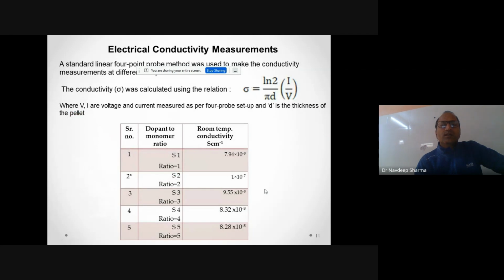And the electrical conductivity measurements by the four-probe method on these samples, the IV study, represent that the maximum conductivity of the sample is shown at 1 × 10⁻⁷ per centimeter. The sample with ratio 2 shows the best conductivity among the samples.